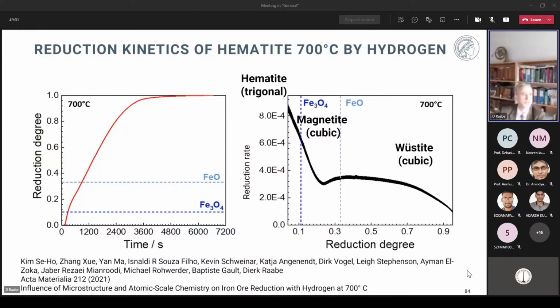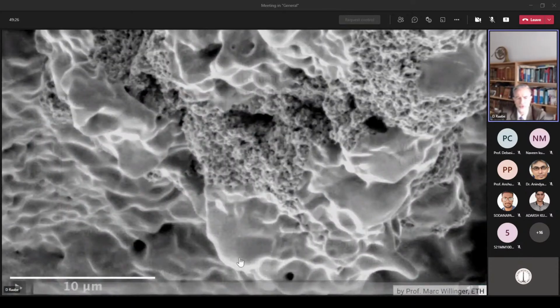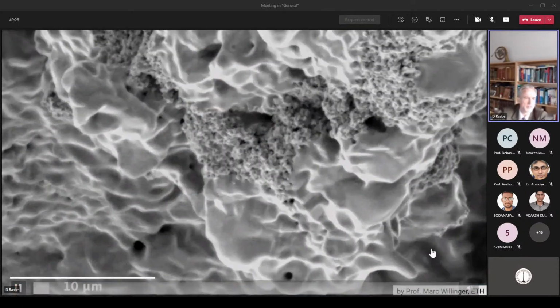And here's such a kinetics when I do that on a commercial pellet at 700 degrees centigrade with just pure hydrogen at 700, as I said. And then you go through that sequence, you can see the reduction rate here, the derivative, and go from the hematite, the original hematite ore, which is trigonal in the oxygen lattice. There you go to the cubic magnetite, further to the cubic wüstite, where it gets very slow, and further, of course, into alpha iron at 700.